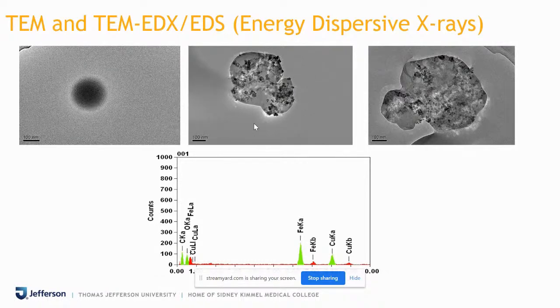doing transmission electron microscopy and the electrons were constantly being fired at a high voltage, the characteristic X-rays were constantly being generated. And luckily, we had a detector to detect these X-rays, and voila, you can see over here in the graph at the bottom, you can see the Fe Ka peak and the Fe Kb peak. Ka is K alpha and Kb is K beta X-rays, and Cu is coming from the background because these samples were a nanodispersion that we put on a copper grid when we were doing the TEM measurement. So the Cu is coming from the background signal of the copper grid on which the nanoparticle is placed. And the Fe signals that came out confirmed that these crystals that you see in the images were coming from the Fe particles.